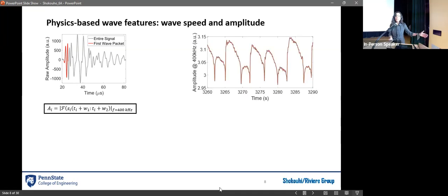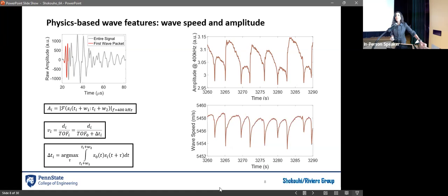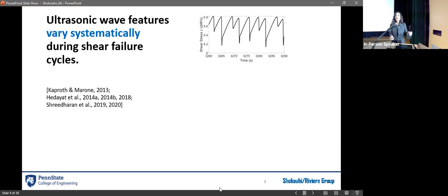How do we do that? We calculate the amplitude in the frequency domain. You could also do it in the time domain, of course. And for wave speed, we use cross correlation to get the time shift with respect to a reference, and then we have wave speed versus time. So for each of these friction experiments, we have a history of wave speed and amplitude with time.